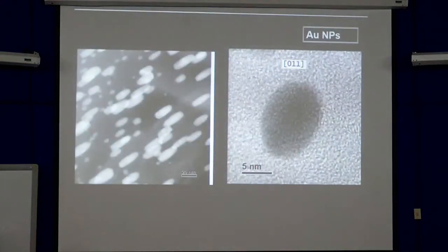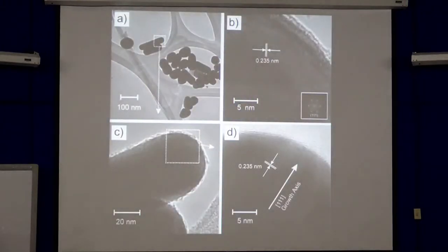These are prepared also by ion implantation, but we move the material in order to obtain an anisotropic sample. As you know, the light has a vectorial nature. If the light has the vector of polarization in this direction, it absorbs in a different way than if the polarization is orthogonal. These are also gold nanoparticles.